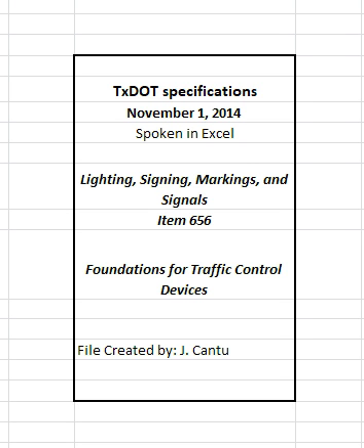Use Class A concrete for non-reinforced drilled shafts. Use Class C concrete for reinforced drilled shafts. Use Class B concrete or polymer concrete composed of borosilicate glass fiber, catalyzed polyester resin, and aggregate for traffic signal controller foundations. Use drilled shaft or galvanized steel screw-in type foundations for roadside flashing beacon assemblies. Use reinforcing steel when required.